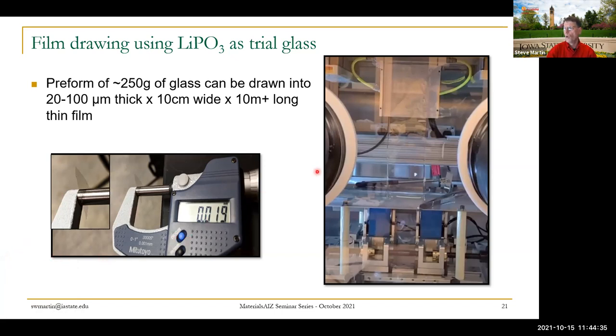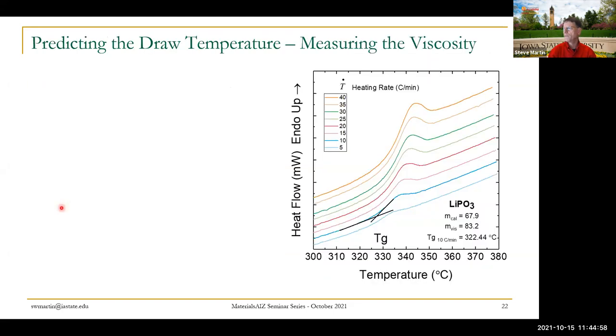So we can pull these films. Here we have about 250 grams of glass that Adriana pulled out. We get 20 to 100 microns thick, about 10 centimeters wide. We get meters of that film out of that one preform. And here you can see one drawn at about 19 microns. You can see the little piece of glass that we've fractured off and are measuring the thickness of there.